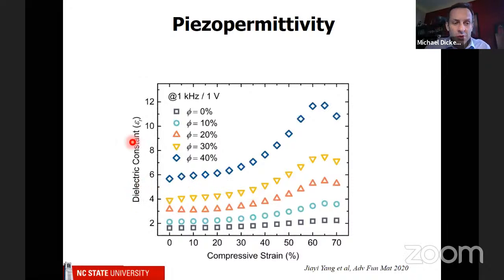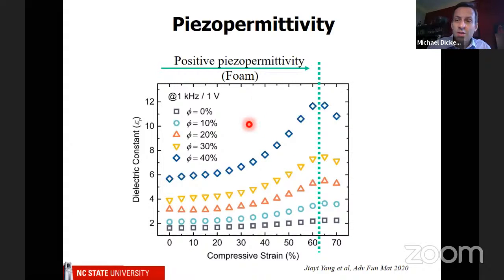So we went back and we measured the dielectric constant of these squishy foams that have liquid metal in them. And again, these squares are 0% liquid metal, 10, 20, 30, and 40%. So you'll see at 0 strain that adding the liquid metal takes the dielectric from almost 1, that's like air, that's nothing, to about 6. So that's a big improvement. But the other thing is the dielectric increases. And the reason it increases is that we are squeezing a foam, so we're replacing the air with actual material.